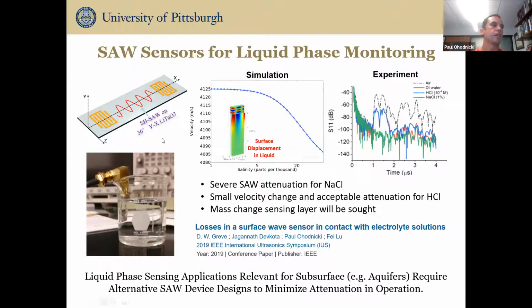The solution to that is to use an alternative orientation of your substrate, which creates what's called a shear horizontal acoustic wave. So the acoustic displacement is in the plane of the surface acoustic wave device. That allows you to operate in solution phases, and that allows you to potentially extend these types of devices to applications like pH sensing in well bores or pH sensing in carbon storage applications, for example.